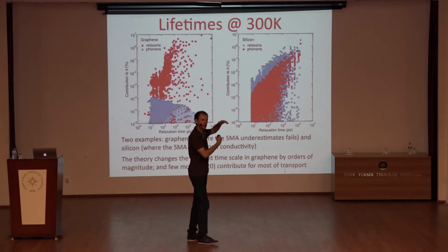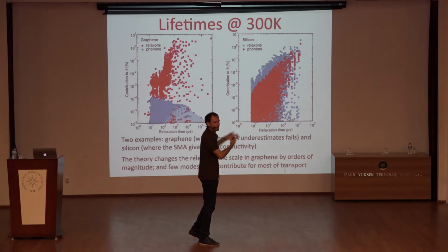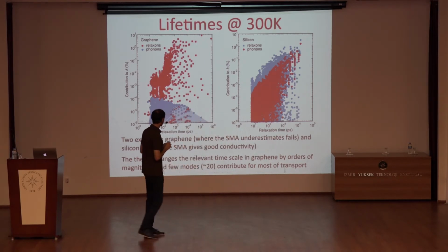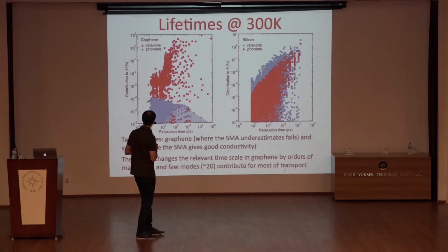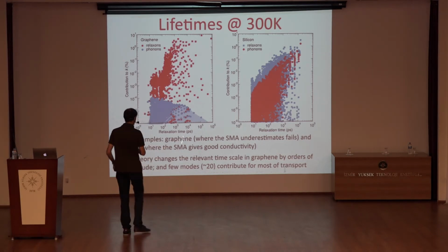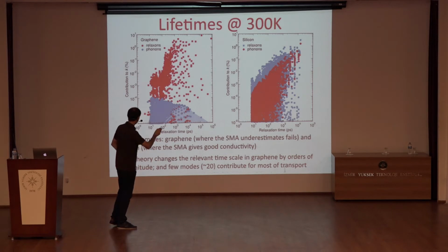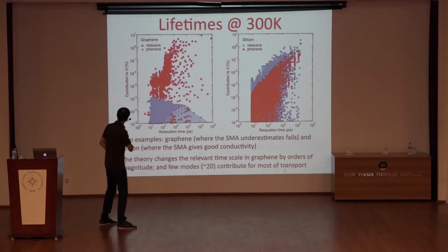This comparison is not completely equivalent because I'm looking at two different quantities. So keep in mind that when you look at this plot. This is also something that you can get with the Matthiessen rule, which has contributions 1 over tau from normal plus 1 over tau from Umklapp and the isotopic stuff.